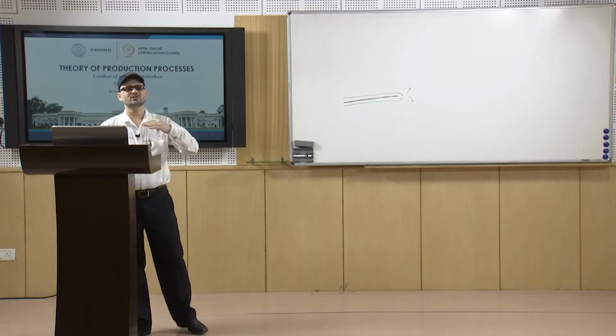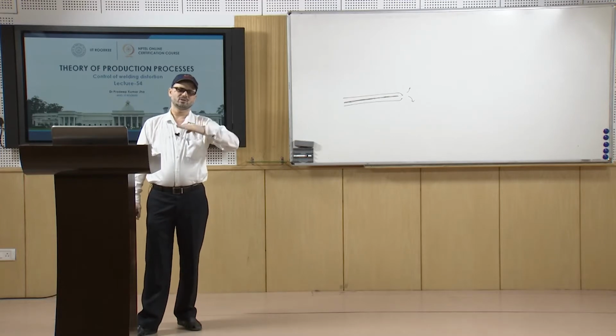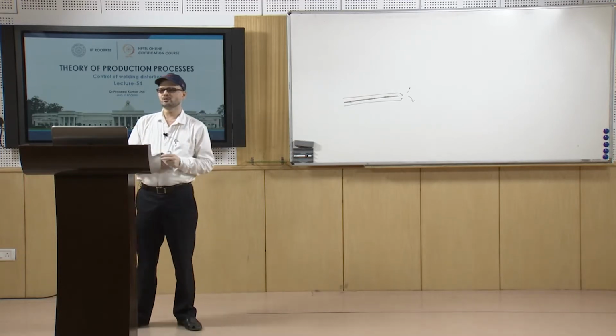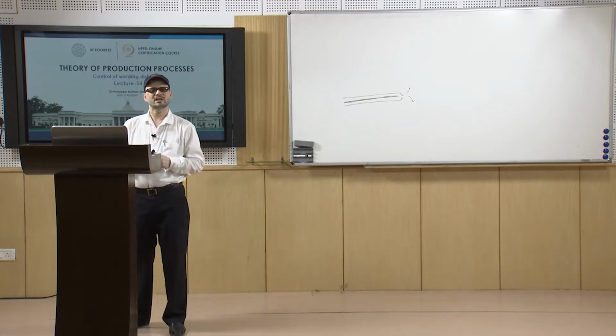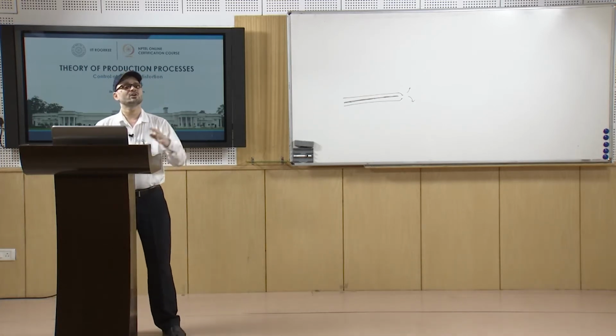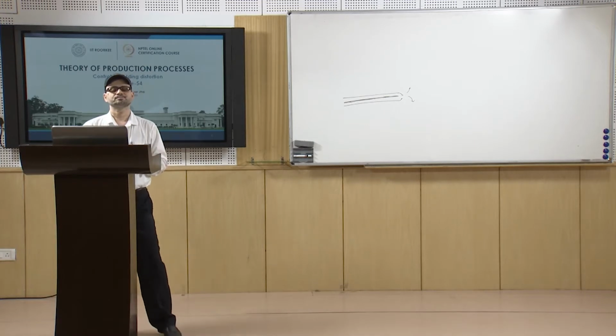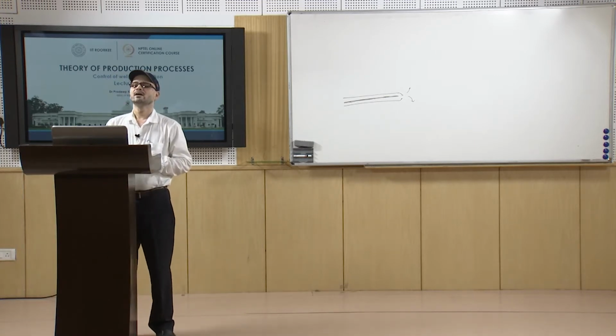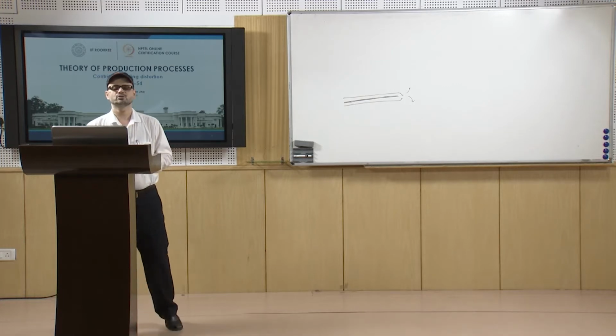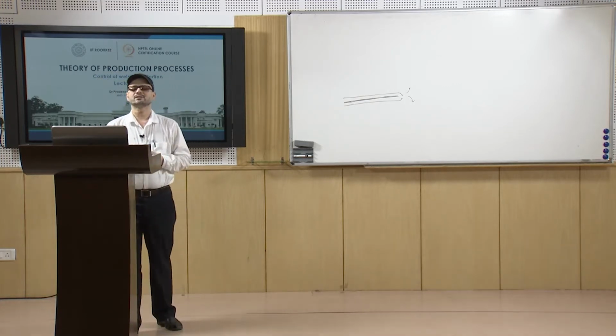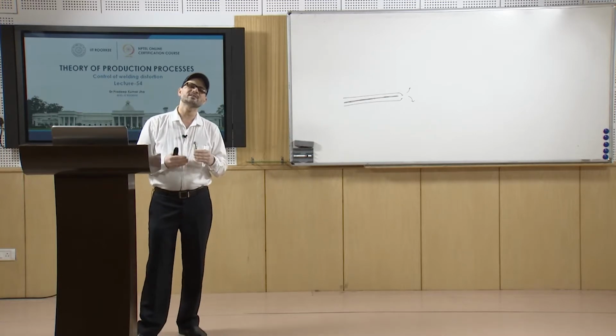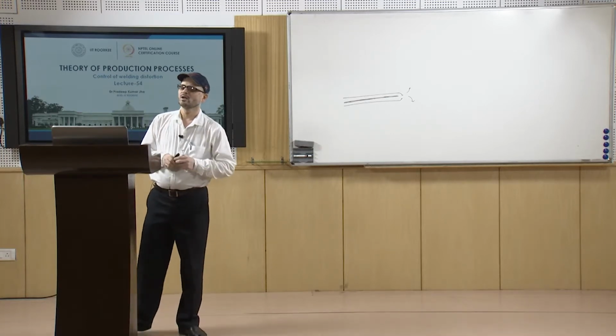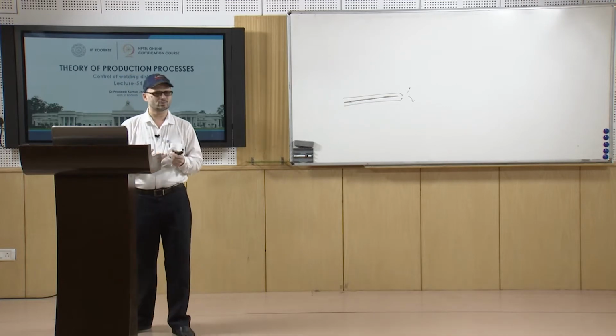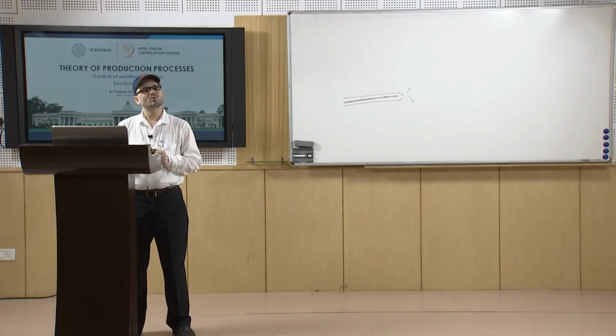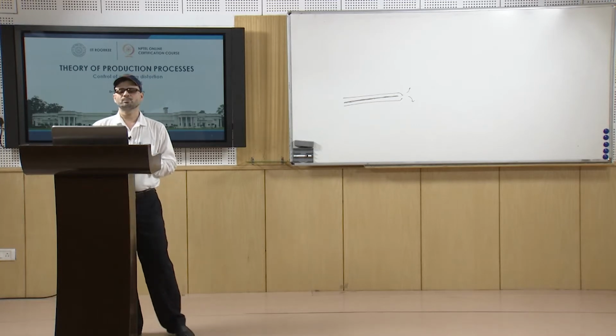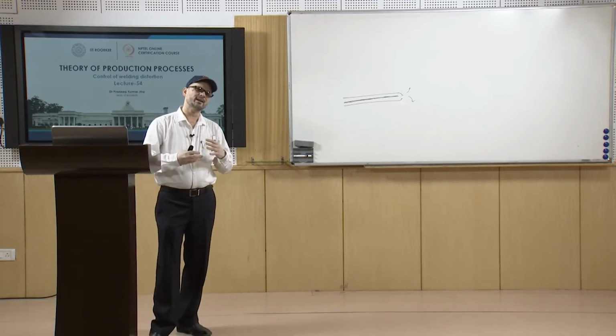So, you try to follow the welding in the direction in which you have maximum degree of freedom. That way, that is the better practice of controlling the distortion. Then you have least weld metal deposited. Basically we know that as the quantity of weld metal deposit becomes more and more, the amount of contraction will be more. So, that will lead to more distortion. So, you should see that you are not putting any excess metal.